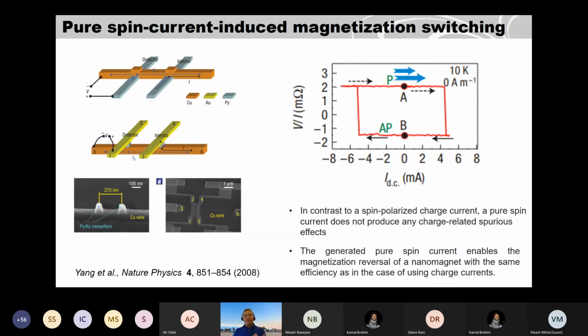Then the question was, let's say you can transport spin in non-magnetic material, but how can you use it? In 2008 already people had shown that if you have a nanomagnet, for example in this picture, some permalloy nanopillars, you can send a spin current in this copper wire and switch one of these magnets just by applying a current without magnetic field. So this is the zero magnetic field here, but at low temperature. You apply this DC current. It should be a pulse current, not to heat up the samples. And so you can switch the magnet and you can see this hysteresis behavior. So this is how a pure spin current induced in this copper channel can switch the magnetization of an electrode. So that can be used for spin logic applications.